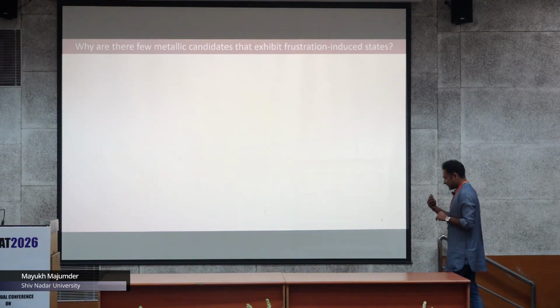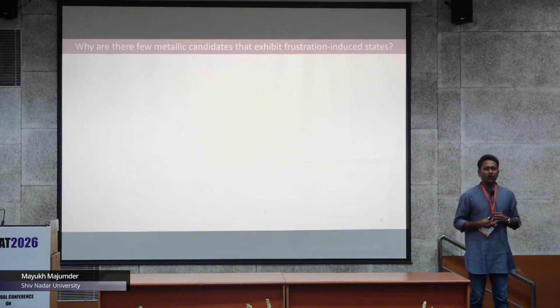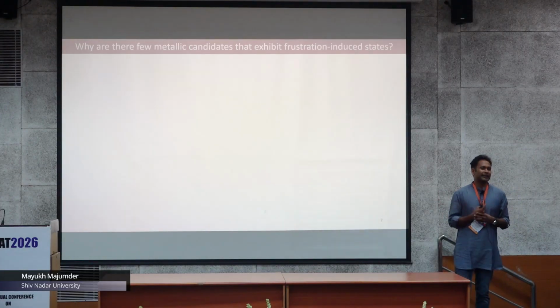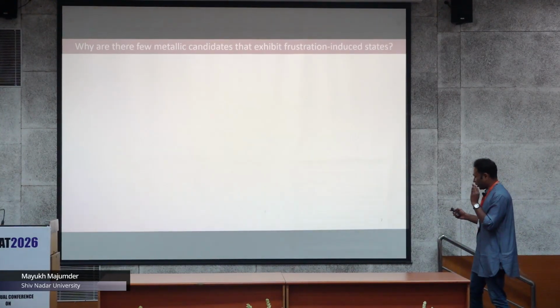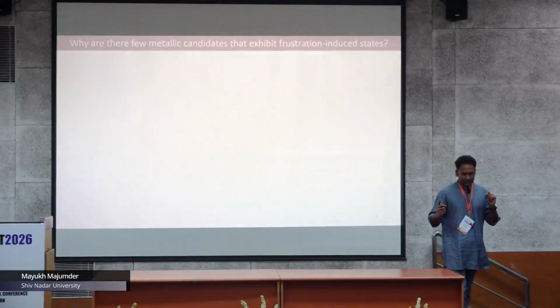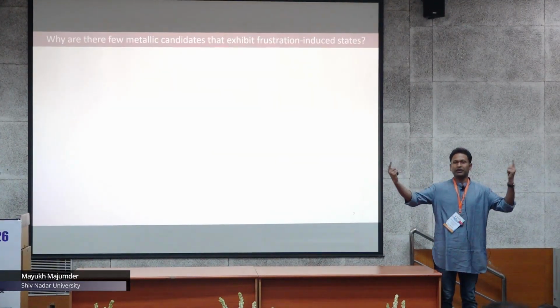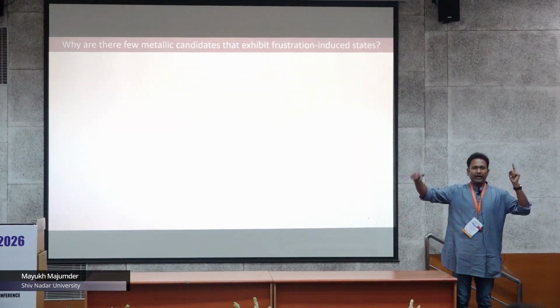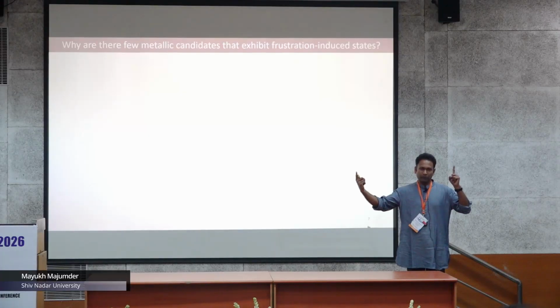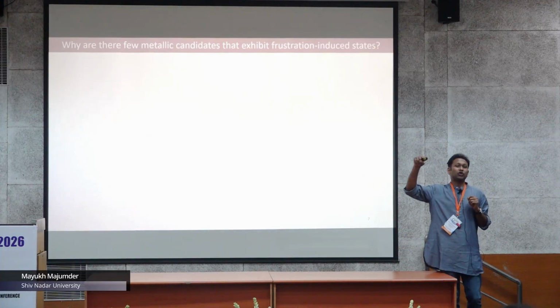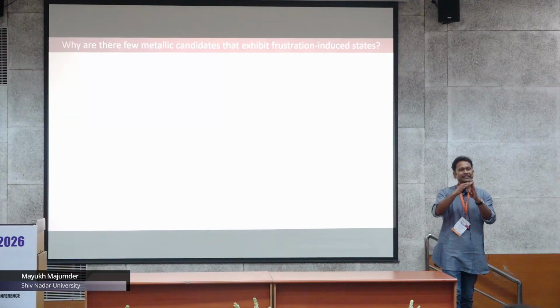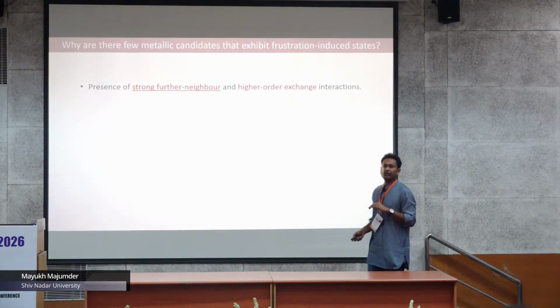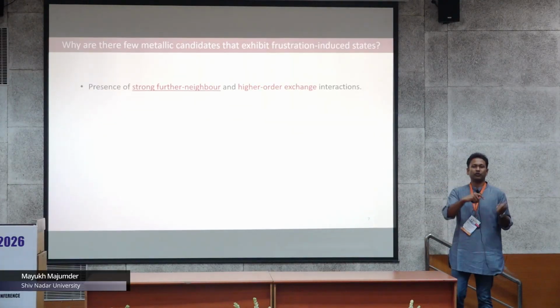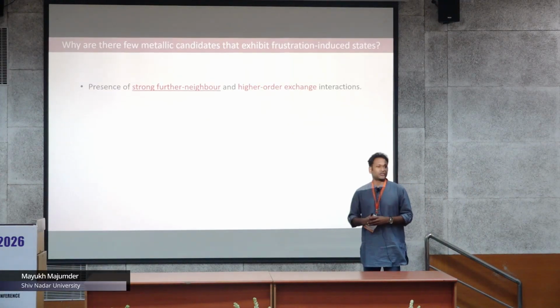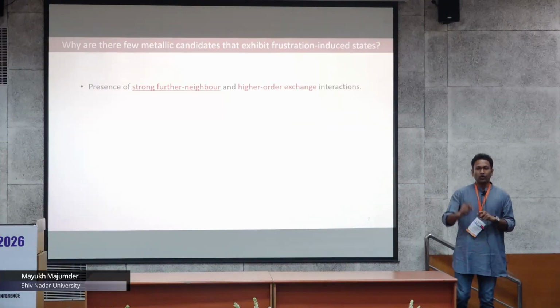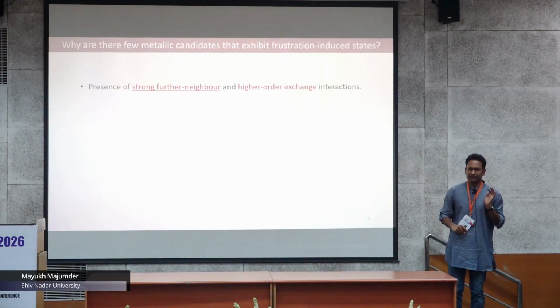So now the question is, as I mentioned in the beginning, why there are fewer interesting frustration-driven states in metallic systems. What we feel is that in insulating systems, if you consider the further neighbor interaction between the spin moments, it decays exponentially, whereas in metals, since it is driven by the RKKY type of interaction, it doesn't decay exponentially but follows 1 over r to the power 3, right, as you know. So there is a good chance that in metals you have relatively stronger further neighbor interaction compared to insulating systems, which can diminish the presence of frustration in most metallic systems, even though the magnetic moments are arranged in a nicely frustrated structure, okay?